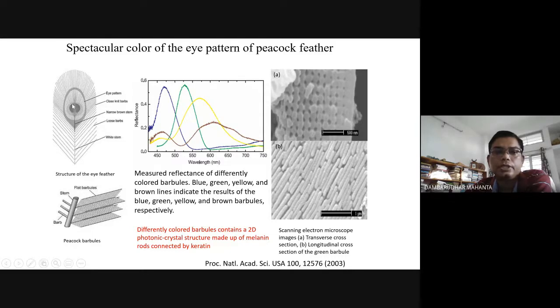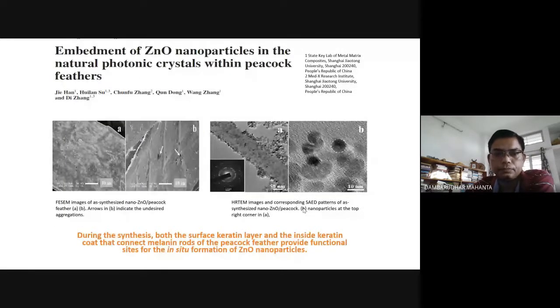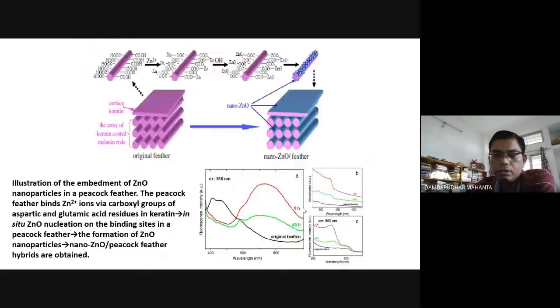So you have 3 regions. For 3 different, distinctly different regions, you have different reflectance spectra, you could see here. And these are actually photonic structures. Let me tell you, you have actually melanin rods. These rods are hexagonally arranged, and these are coated with keratin. So melanin rods coated with keratin is basically responsible for this bright coloration feature, and the color of this eye pattern will depend on the lattice spacing or the periodicity.